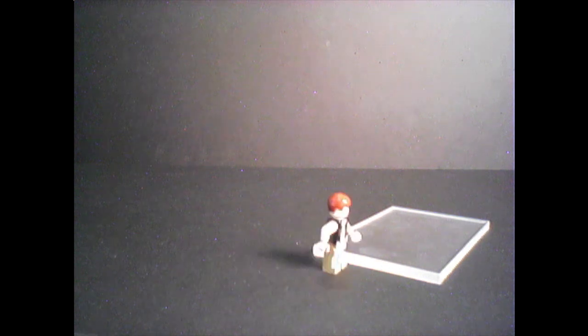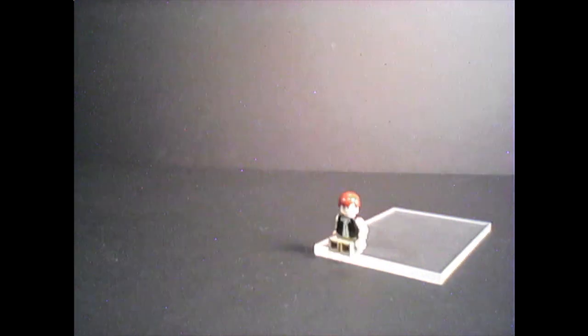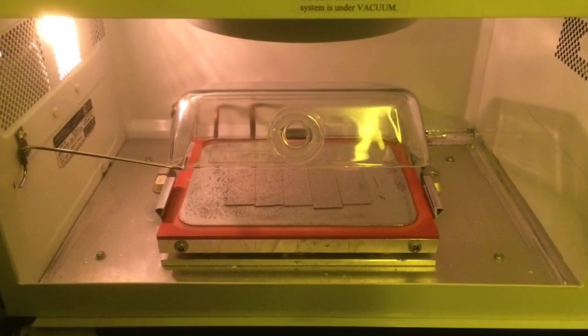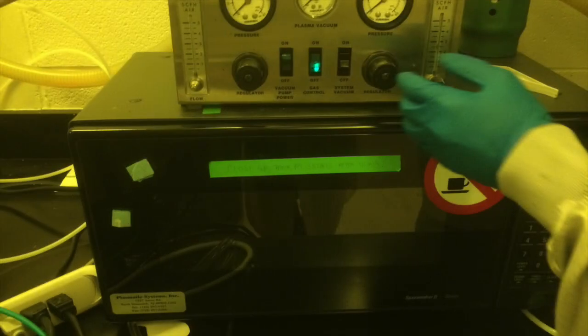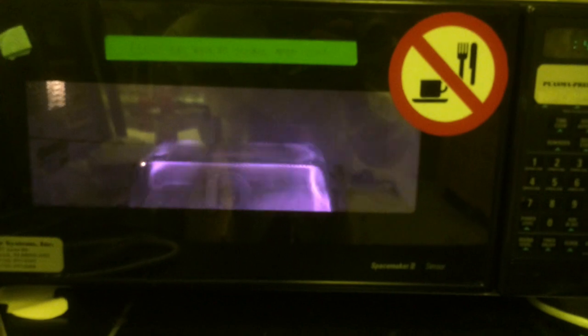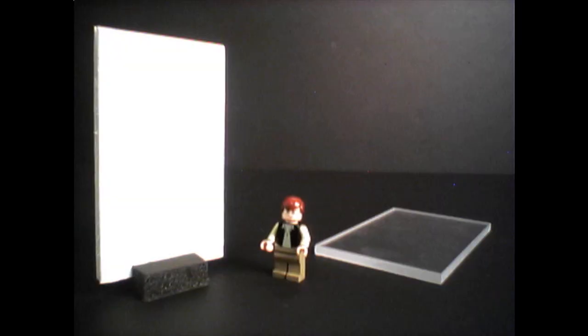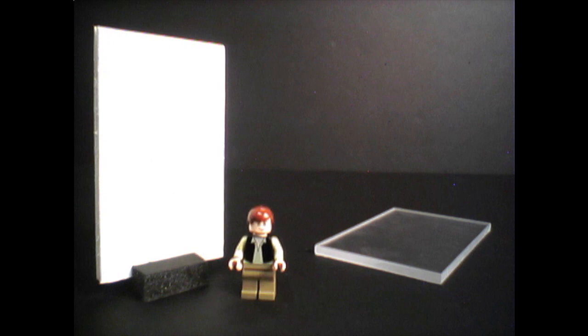Here's Han next to the top surface of our glass sheet. Han, what are you doing? Oh no, you've made the glass dirty. Sorry. Now we have to clean it with an oxygen plasma. Here we're using a microwave to energize oxygen molecules and create a plasma, which breaks molecular bonds and destroys carbon-based contaminants on the glass surface. Okay Han, so now that our glass is clean,